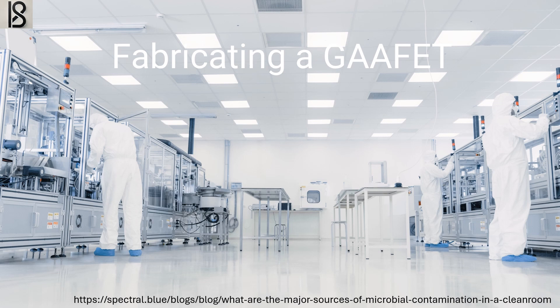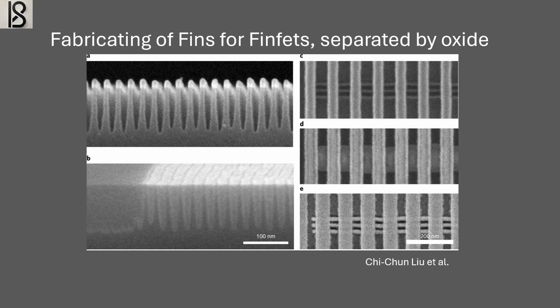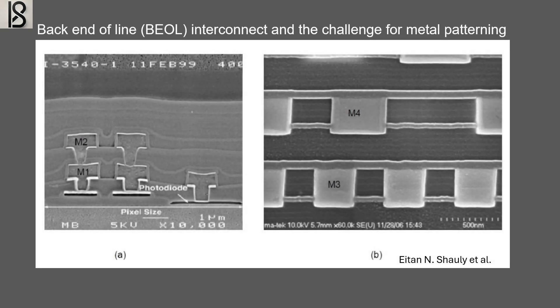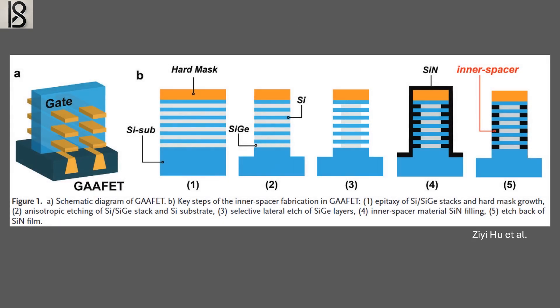The process for fabricating a FinFET is very similar to that of manufacturing planar transistors, which is significant, as the semiconductor industry tends to progress gradually rather than undergoing drastic change. The key innovations were creating dense, highly regular clusters of fins, which are patterned onto the silicon substrate using a specific form of double patterning lithography. Following this, wells are formed to eventually create the source and drain. A temporary dummy gate is added to help construct the rest of the gate stack, electrically isolate the transistor, and is then removed to allow for the formation of the actual gate. Using a deposition technique known as epitaxy, multiple layers of silicon and silicon germanium are added on top of the silicon substrate, creating what is sometimes called a superlattice.